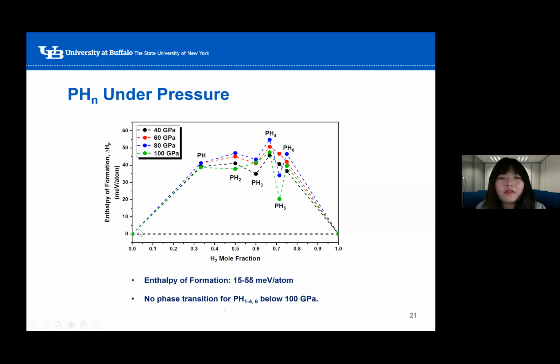So we carried out our evolutionary searches at 40, 60, 80, and 100 GPa. And similar to the previous project, we studied the stoichiometries of PH to PH6, and they are all metastable. Their enthalpies of formation fall into the range of 15 to 55 meV per atom. Because there were no phase transitions for PH1 to 4 and 6 below 100 GPa, and the experimental measurement was taken at 83 GPa, we decided to focus on the results we got at 80 GPa.